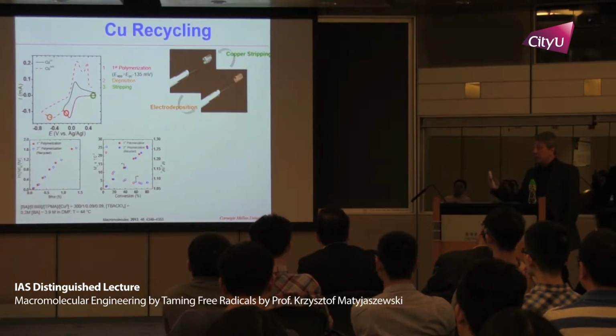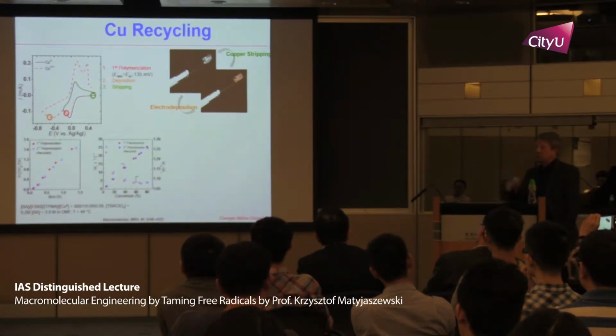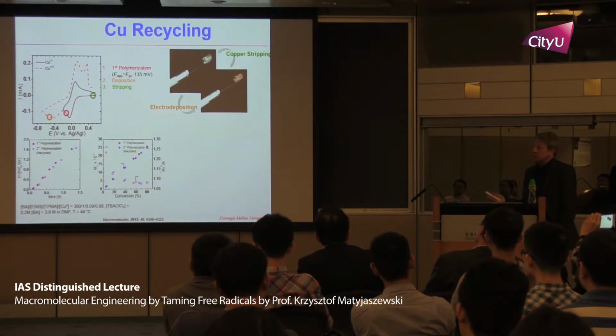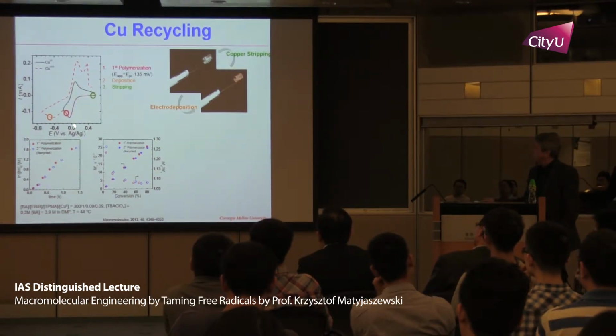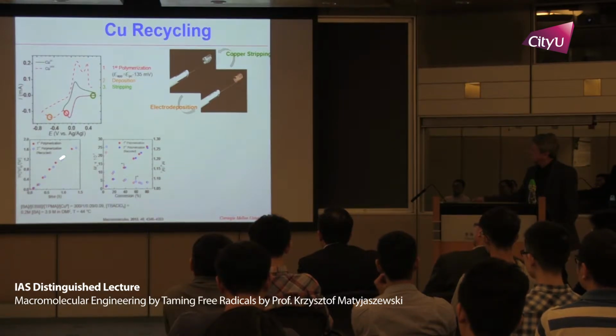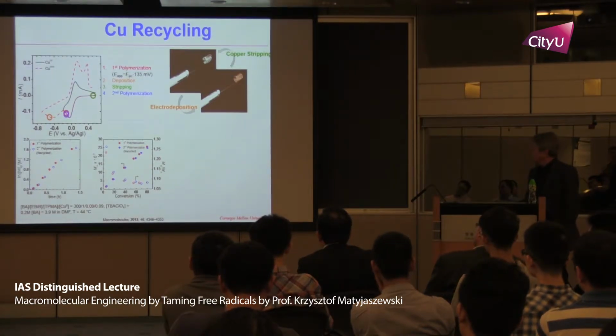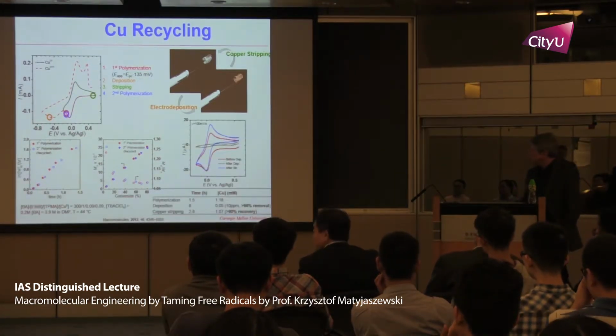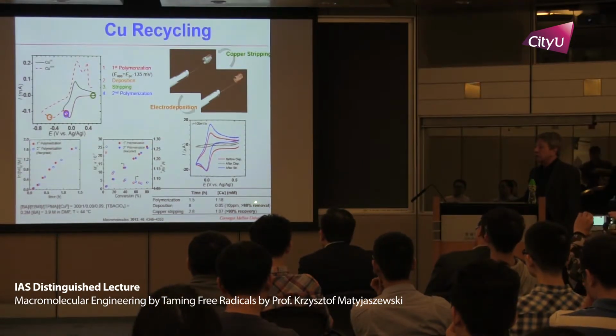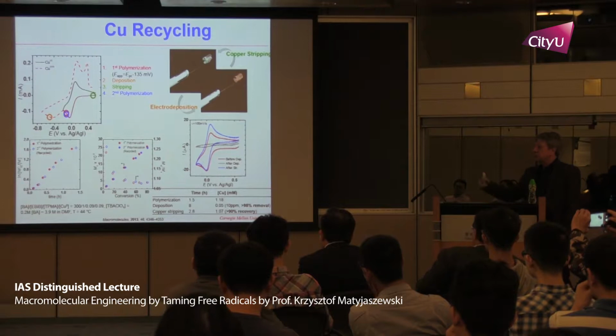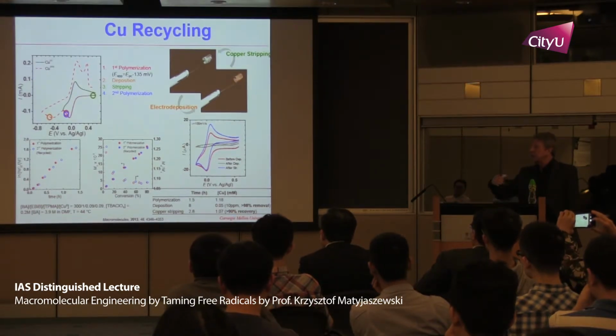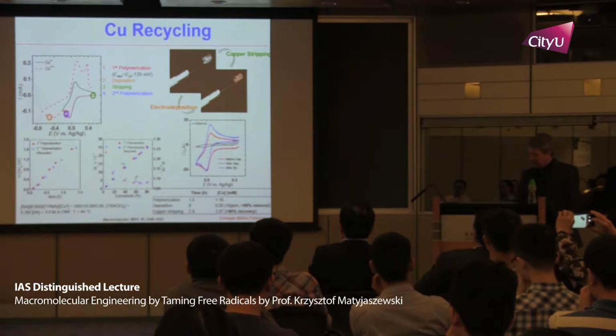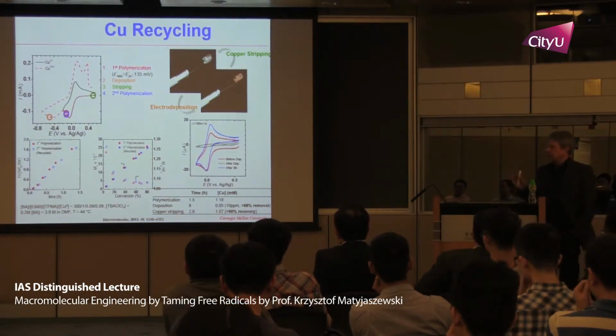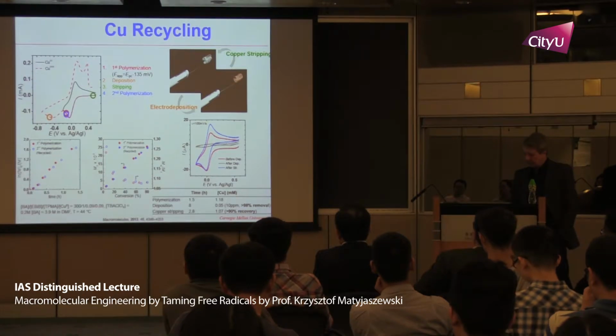So this is really very good news, because I can remove and replace copper. Under these conditions, polymerization essentially stops, because there is no more catalyst inside. But then I can put it back again, and if I go to the same potential, I get the same kinetics, same evolution of molecular weight, low dispersity. So you can remove probably 98% of copper from the system, and then you can recover 90%, depends how long you wait for this copper to come back from the electrode. So this really gives me the possibility of making temporal control of polymerization.